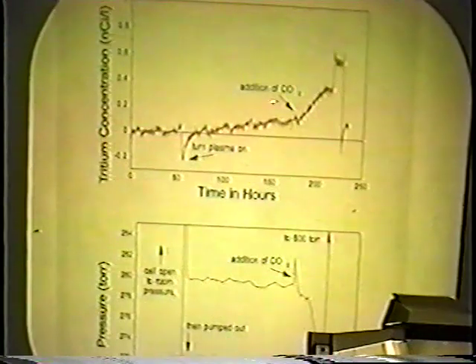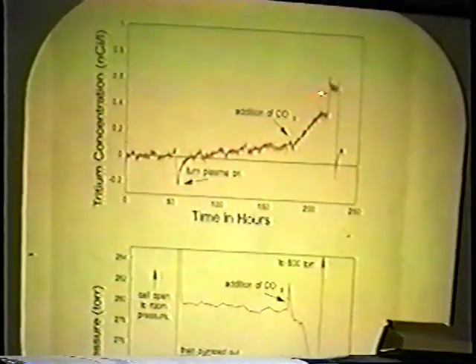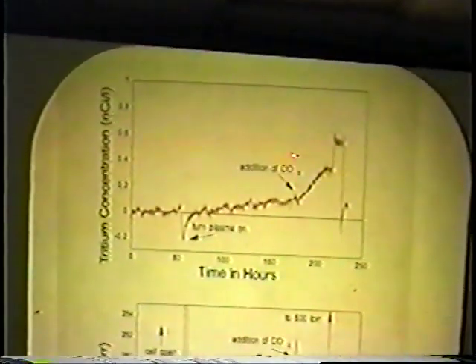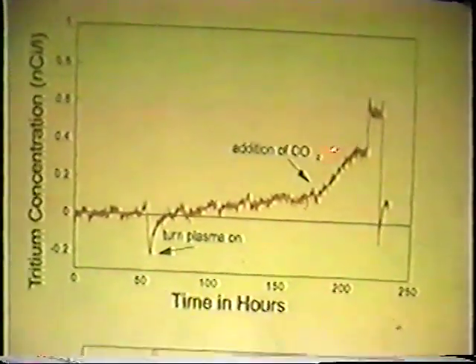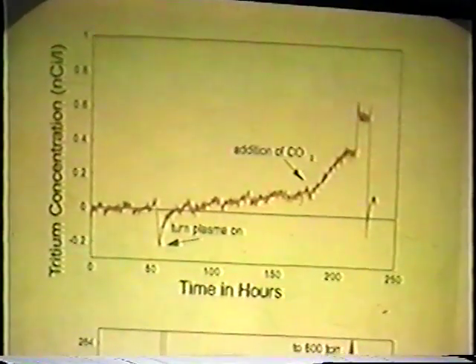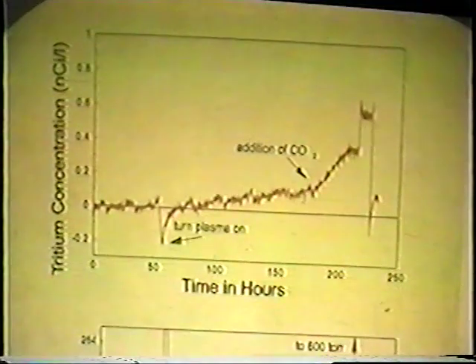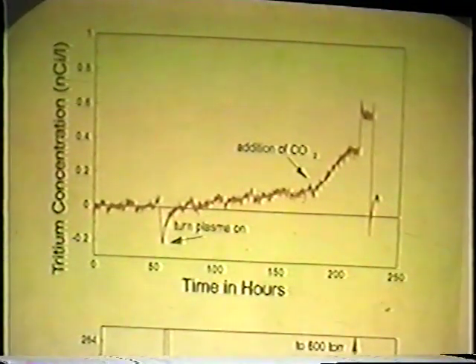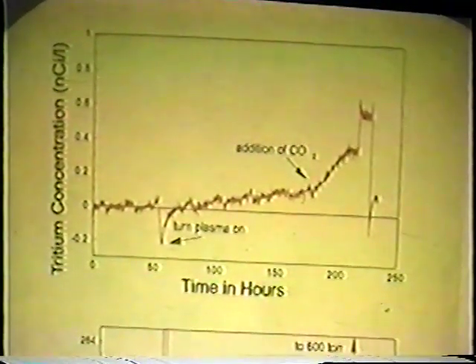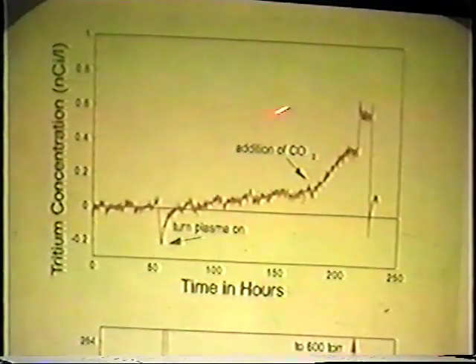One of the other tricks that we've tried, originally what we had done was put argon into the system, because argon will apparently at lower pressures help you get the D+. And so we've done a number of gas additions. Well, the only gas addition that really has done anything has been the addition of CO2.